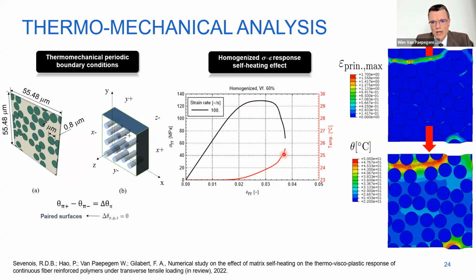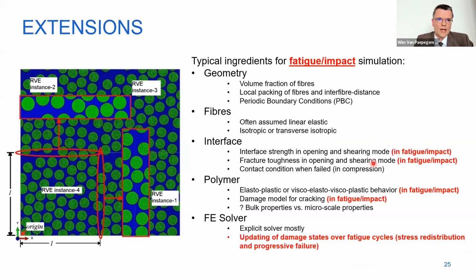You see that the temperature barely rises, but this is the homogenized temperature. If you look locally in your RVE, you see a very high localization of the strain and a high increase of the temperature, 50 degrees. So here we have a model for the polymer that couples the plastic deformation to the heat dissipation, and the heat in turn will soften the material because this is a thermoplastic matrix and the glass transition temperature is close to 50 degrees in this case for polyamide 6, and you get a softening. So this is a self-sustaining effect.